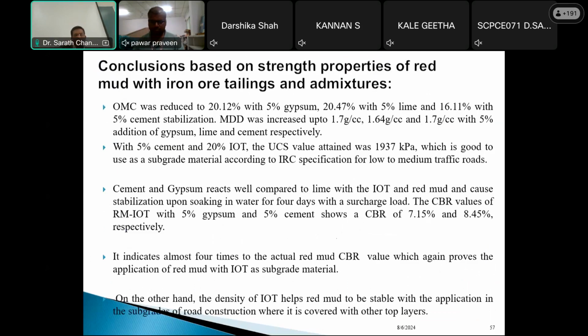Next, with the iron ore tailings and the admixtures with the red mud. With 5% cement and 20% IOT, the UCS value attained was 1937 kPa, which is good to use as a subgrade material according to the IRC specification for low to medium traffic roads. And cement and gypsum react well compared to the lime with the IOT. The red mud and IOT stabilization was tested on soaking in water for 4 days for the subgrade.